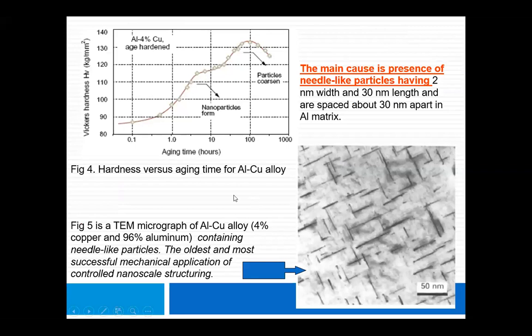Not only this, around 50 years ago or before that, age hardening technology was existing. In metallurgy, it is a well-known example that we still use. There is no change in the composition. Please remember, composition remains the same, but by creating nano precipitates in the matrix, you can enhance the hardness by about 50%, 60% or more by increasing the nano-size precipitates. You can see that when we increase the aging time, hardness increases from 85 units to more than 135 units. So why does this happen?